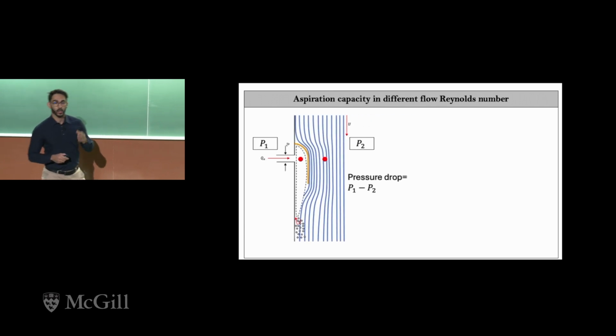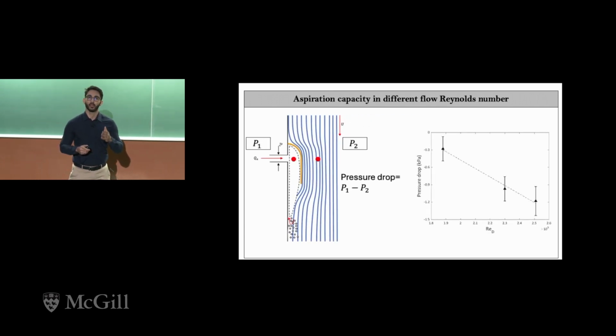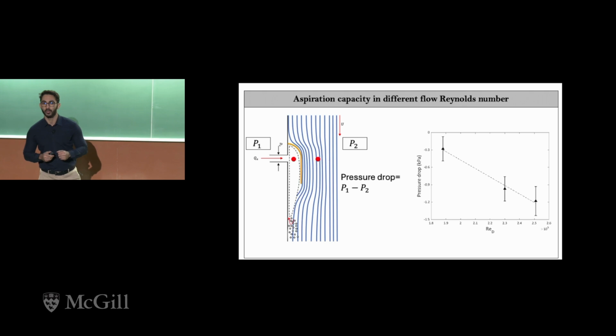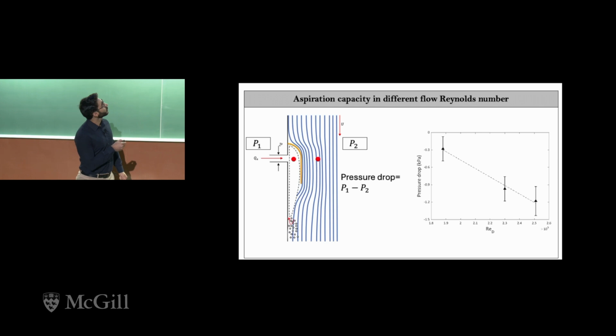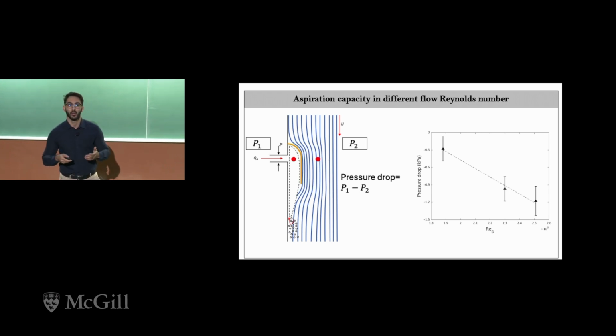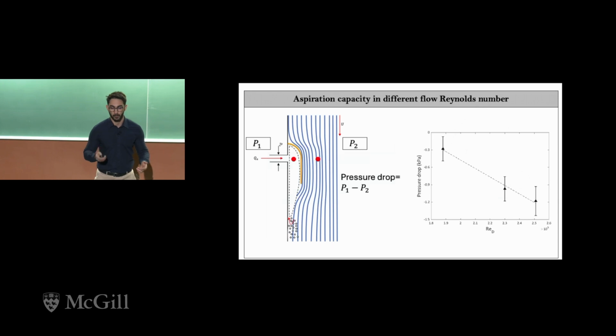To have self-aspiration using the elbow deflector, we should have negative pressure drop across the deflector. And by looking at the results here, we can see that by increasing the water speed, we have a decrease in the pressure drop, and it makes it more negative, which is exactly what we needed to have air self-aspiration.